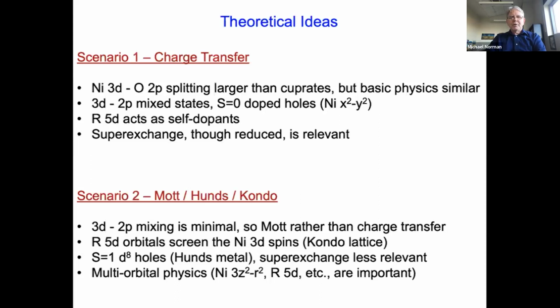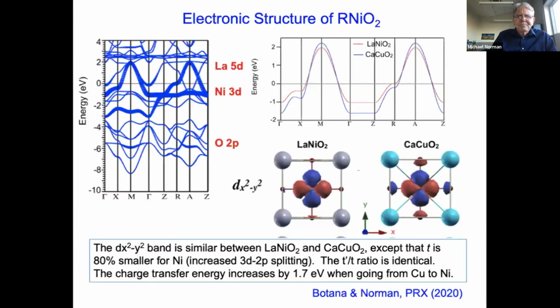3z squared orbitals come into play, so it's more like a Hund's metal. And then, of course, the 5D rare earth orbitals can screen the nickel D, so you get some sort of Kondo physics coming into play as well. And so this is sort of the second camp, and it could well be that both aspects apply to the real material. That is, you're sort of in an intermediate regime between this charge transfer cuprate scenario and this Mott Hund's metal phase, which of course makes it more difficult to treat theoretically.